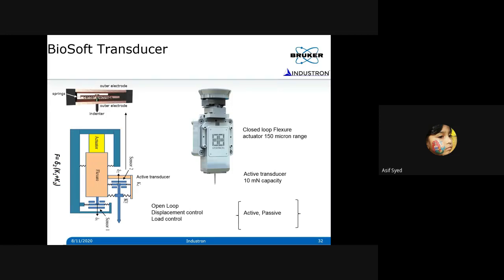The second part is that the transducer over here, which measures the displacement, is nothing but our electrostatic transducer itself, which means that it can actuate and generate force. So we call it a null sensor mode, where we actuate and keep the center plate at the center position all the time. At the same time, using this actuator, we can push onto the material. So now we don't lose the sensitivity. We have a very highly sensitive force measurement, and at the same time a very large displacement range.